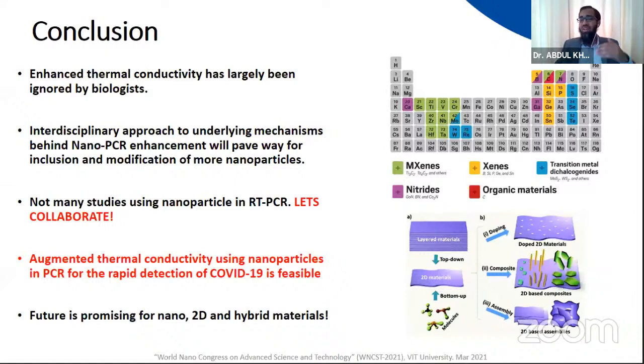So when you are reducing half the number of cycles, you're actually talking about a reduction of 50% time, which is really huge. Nevertheless, when I said 8 to 10 hours, it is taking into account all the preparatory steps, which may not necessarily be repeated every single time. Preparatory steps are only done once you have new reagents and so on, once you need to establish the optimization. So I hope this answers your question.